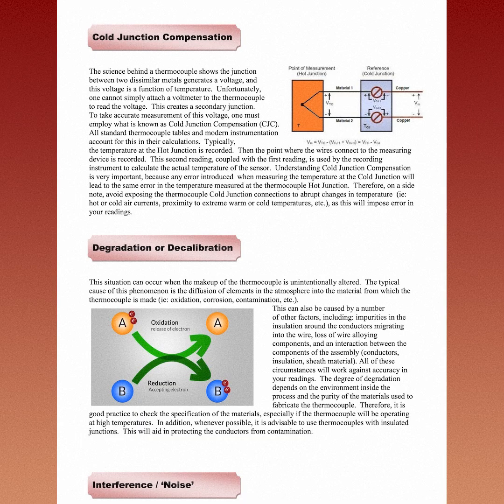Degradation or decalibration. This situation can occur when the makeup of the thermocouple is unintentionally altered. The typical cause of this phenomenon is the diffusion of elements in the atmosphere into the material from which the thermocouple is made, that is, oxidation, corrosion, contamination, etc. This can also be caused by a number of other factors, including impurities in the insulation around the conductors migrating into the wire, loss of wire alloying components, and an interaction between the components of the assembly: conductors, insulation, sheath material. All of these circumstances will work against accuracy in your readings.